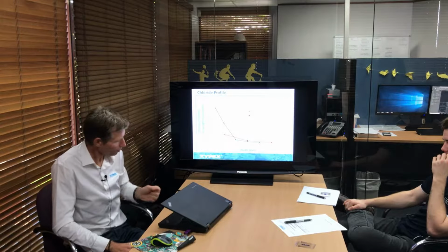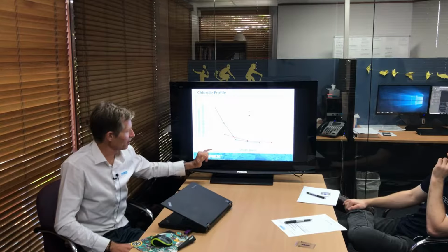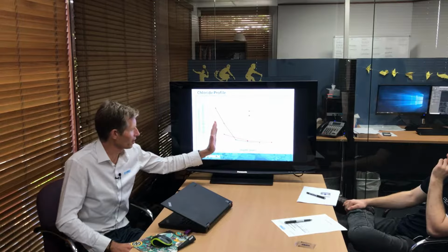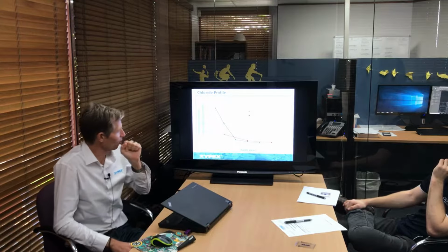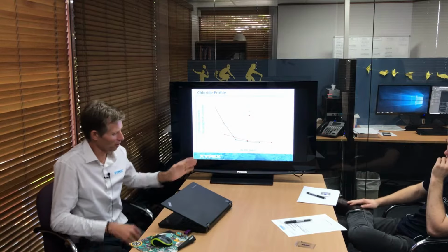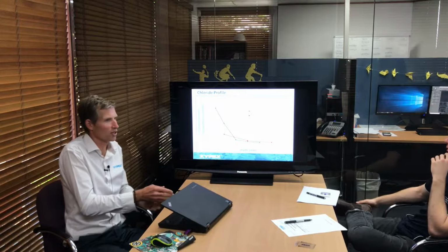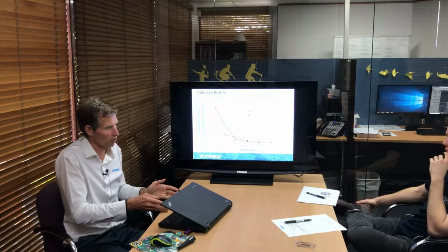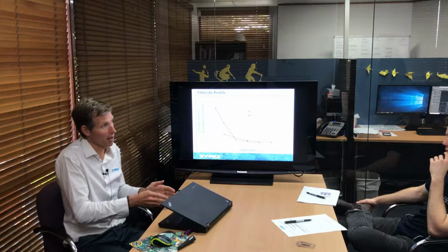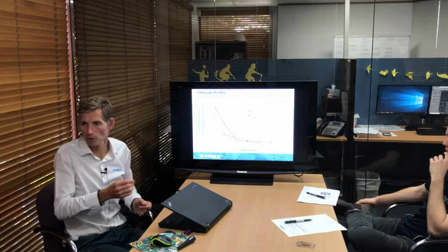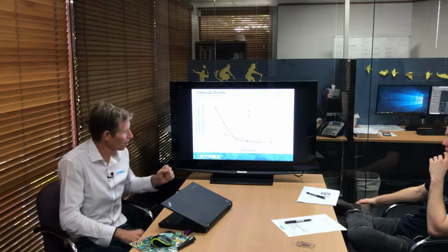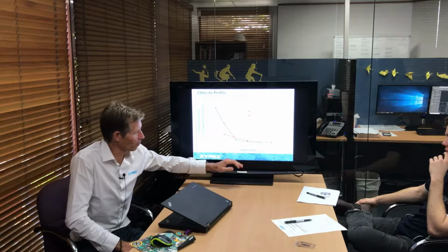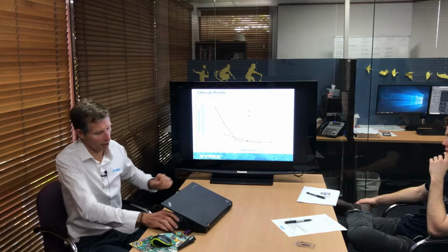Now, as you can see, in that initial 10 mil, you've seen a little bit of chloride ingress in there, and chloride ion content within the concrete. Now that essentially would be what would be seen as your initial skin of the concrete. So that's your surface. This is what Xypex doesn't do, is have any negative impact essentially on the surface profile or texture of the actual concrete itself. But as you can see, when you get into the main concrete element itself, you're getting negligible readings.